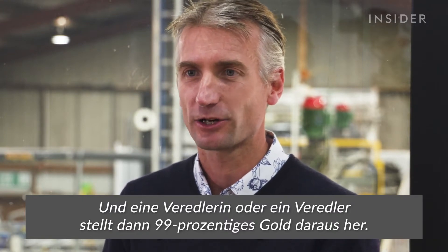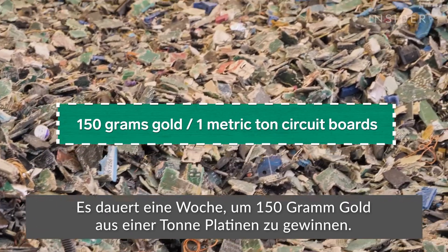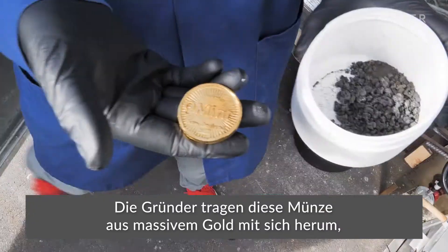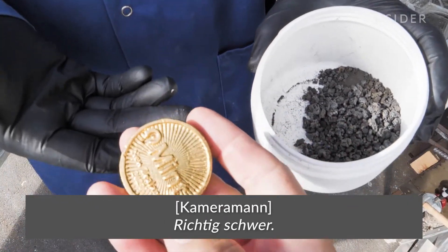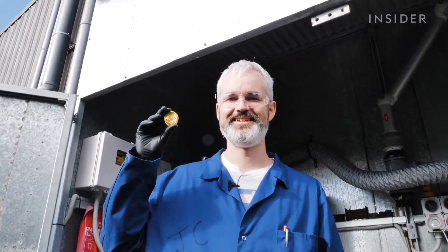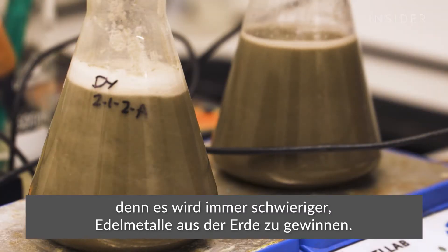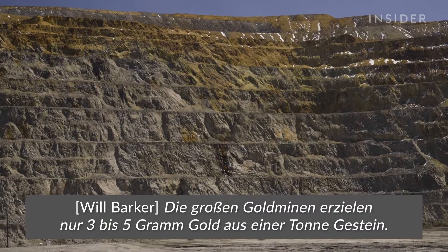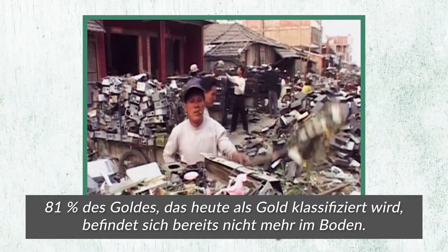The product is a gold-rich ash that goes to a refiner who turns it into 99.99% pure gold. It takes one week to extract 150 grams of gold from one ton of circuit boards. The founders carry around a solid gold coin to show what that looks like. It seems like a lot of work for a small payoff, but Mint's founders say it's worth the trouble because it's getting harder to mine precious metals from the earth — big gold mines are recovering literally three to five grams of gold from a ton of rock.